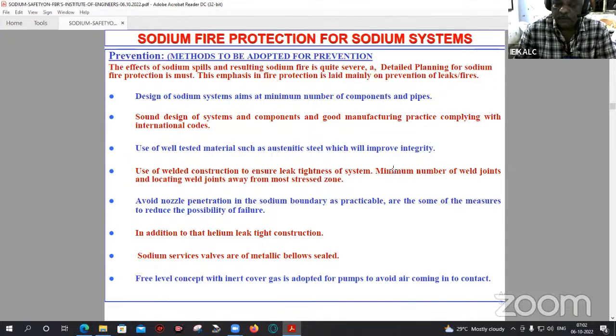Most of the weld joints shall be away from the most stressed zone. Nozzle penetration below the sodium boundary is also avoided. There is helium leak tight construction with respect to quality assurance of the system. The valves are double metallic bellowed valves, twin plied, so there is no possibility of sodium coming in contact unless the bellows fails. And there is a free level concept with inert gas. Sodium is always a pool with a gas space above it, and most of the pumps are centrifugal pumps with the free level concept, used in tanks which have gas on the top.